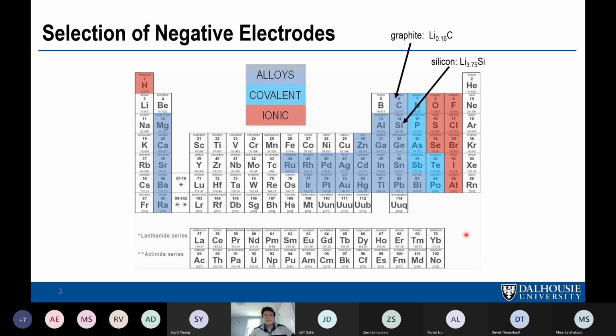So first of all, how do you go about making a higher energy density material than graphite? Well, the first thing to do is to look at the periodic table. And graphite is up here, of course, and you can make LiC6. And there are a lot of other elements that can react with lithium. And the other elements either form intermetallic compounds or alloys, or they form ionic or covalent compounds. And of course, you want the negative electrode to have low potential versus lithium metal. That means the bond strength to lithium should be low. And therefore, if it's forming strong bonds, the potential of these materials is going to be too high.